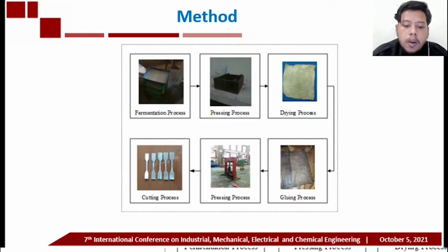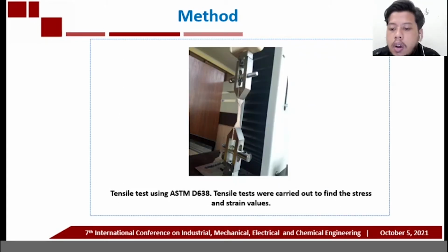After drying, the solid coconut water was coated with glue and pressed using temperature variation 28 Celsius and 80 Celsius with time interval 5 minutes, 7.5 minutes, and 10 minutes. And the last step is the cutting process. Tensile test is carried out after the specimen production process is complete. The tensile test using ASTM D638 was carried out to find the stress and strain value.